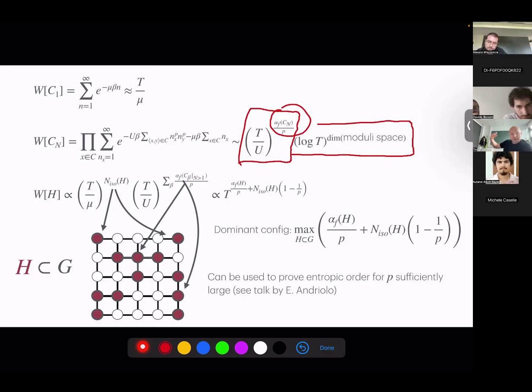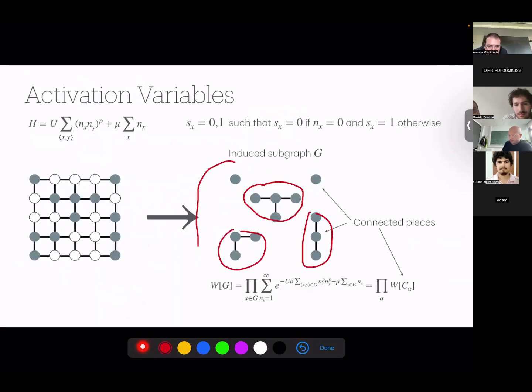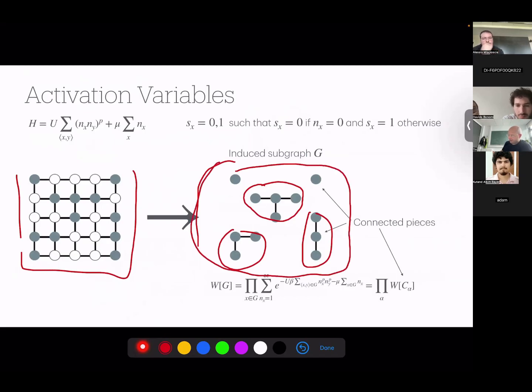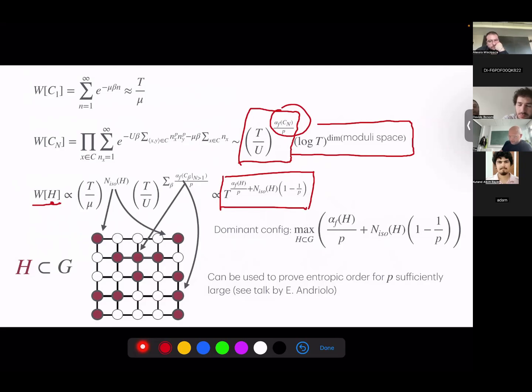Good. Now, in order to see which configuration is the most dominant, because now you know that each configuration in the partition function, labeled by these activation variables, this spin 0 and 1, which tells you whether the site is occupied or unoccupied, has the following scaling. Now, I did some manipulations here. For any given configuration, I have some kind of a graph G, which I called H here, just because G is the whole lattice. So then you can do some manipulations and find that, because isolated points are special, they will appear separately. And the weight of this configuration will have this maximum fractional independent set.